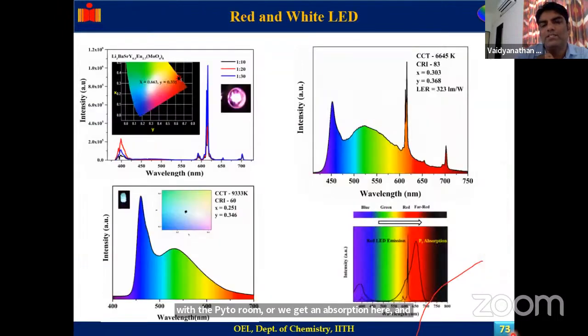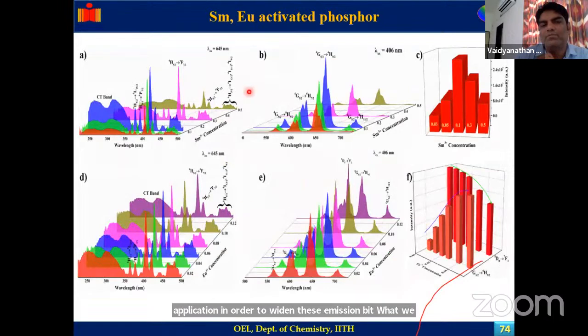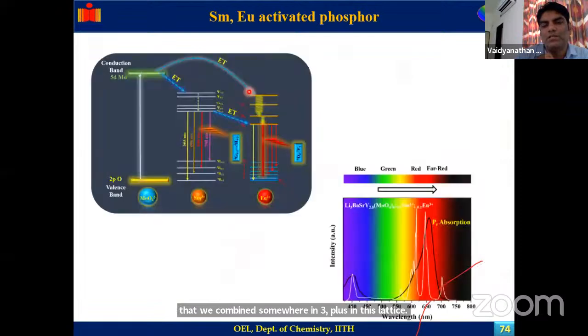In order to widen this emission width, what we did is that we combined samarium 3 plus in this lattice. The samarium 3 plus and europium 3 plus combination gives a very broad emission, which can match up with the phytochrome absorption, and we get a good emission. So we can keep this type of thing in mind.